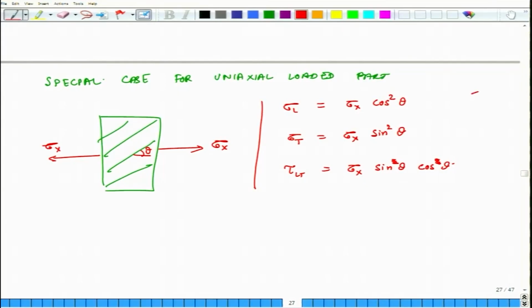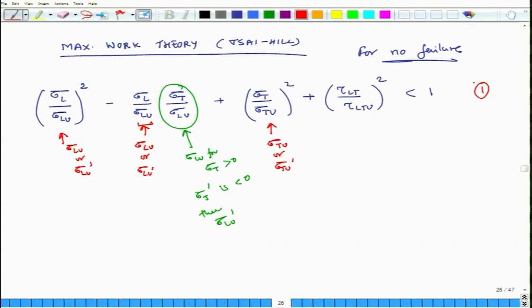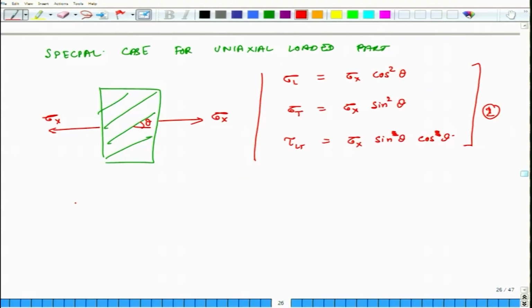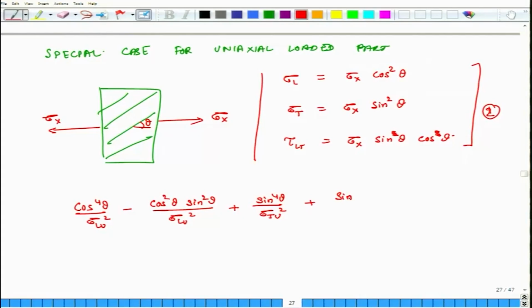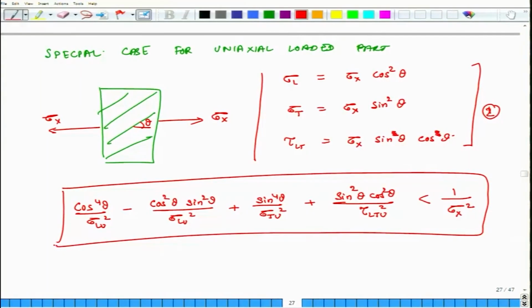LT. And if that is the case, let us say this is equation number 2 and let us call this equation number 1. Then I can put 2 in 1 and what I get is cosine 4 theta by sigma Lu prime sigma Lu square minus cosine square theta sin square theta by sigma Lu square plus sin 4 theta divided by sigma Tu square plus sin square theta cosine square theta by tau LTu square is less than or equal to 1 over sigma x square. So, this is the equation for a uniaxially loaded specimen.